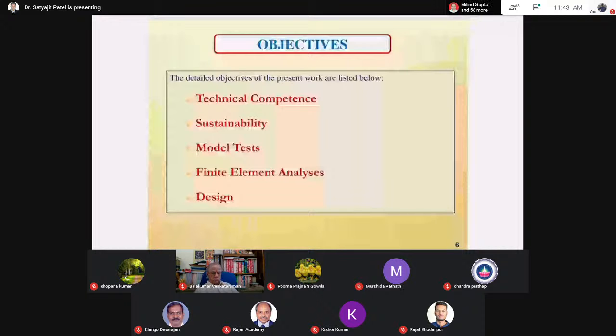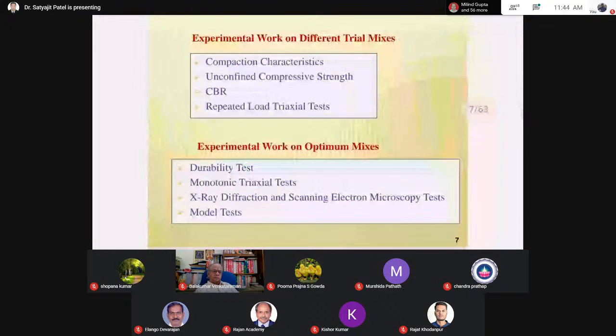So that has been derived. Then experimental work: the basic test, that is the heavy compaction test, has been carried out. Then unconfined compressive strength. As this is a cemented base and cemented sub-base material, UCS is always preferable and comfortable to compare the various mixes, various curing periods and all these things. It is easy to prepare the specimen and easy to conduct a large number of UCS tests. Then CBR has been carried out only for sub-base material, because only for sub-base material you need the CBR value to check its feasibility. And UCS is useful for any cemented material, whether sub-base, base or anything.